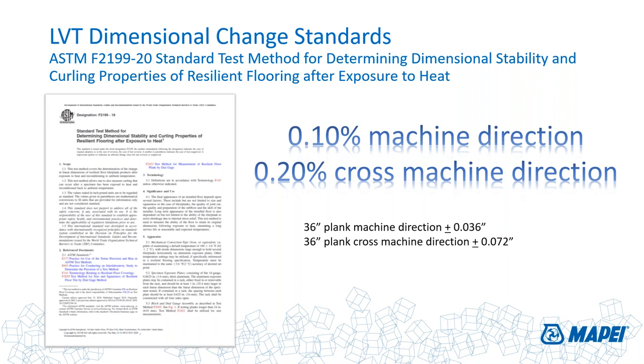But the ASTM F2199 is the standard test method for determining dimensional stability and curling properties of resilient flooring after exposure to heat. And in that, heat is somewhat related to aging. But they're allowing for 0.1% machine direction and 0.2% cross machine direction shrinkage as allowable levels of performance for LVT. So again, the standards exist to let you know that this stuff has a tendency to change its shape over time, temperatures, changes in temperature, and other influences. And those can be some pretty significant changes.